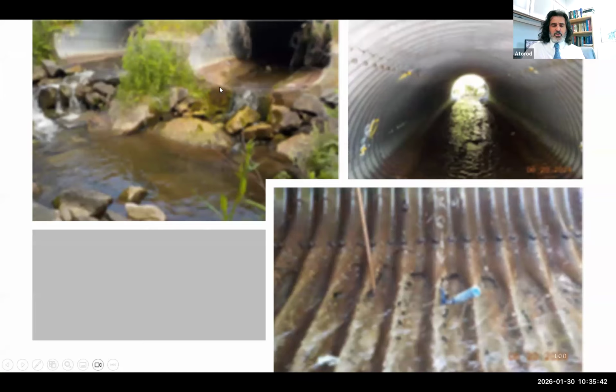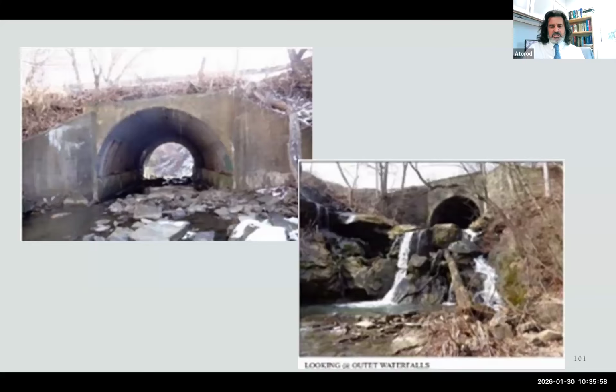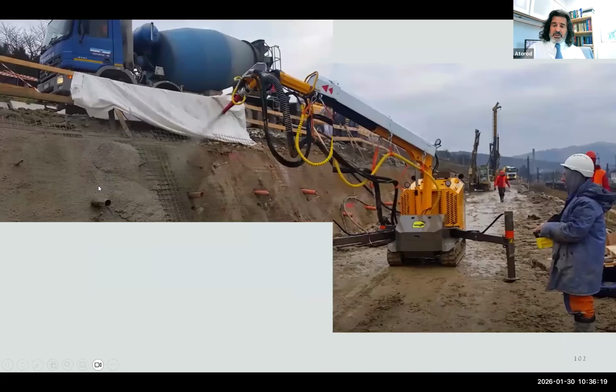The invert is going to be fixed with normal strength concrete, and then we are going to roughen the surface. But then we are going to spray the entire 57-foot long culvert all the way around with the UHPC. That's coming up in June of 2026. And then another one is going to be strengthened. It's got a sidewall, and there is no need for the invert in this case, but we're going to be spraying about a couple of inches of UHPC all the way around, also the sidewalls.